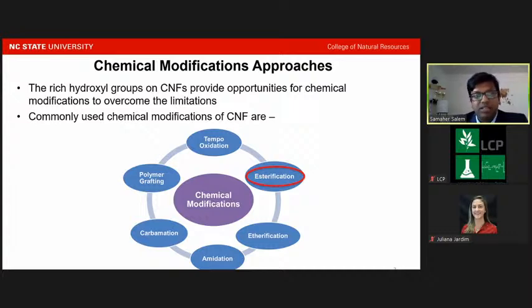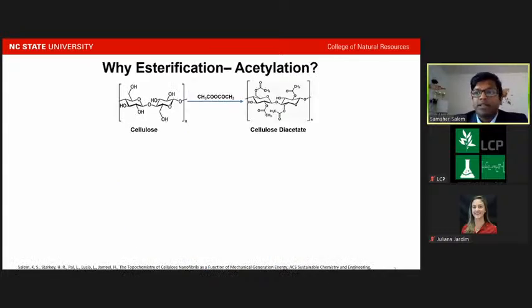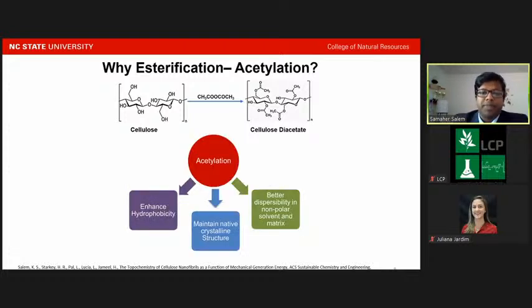I have chosen esterification for chemical modification. Now, what is esterification or what is acetylation? Esterification is a kind of acetylation process where the acetyl group is bonded to the cellulose hydroxyls. This has a few benefits: the degree of substitution could be kept below 1.5, where it enhanced the hydrophobicity, as well as maintained the native crystalline structure. And it also made the CNF better dispersible in nonpolar solvents and matrices.